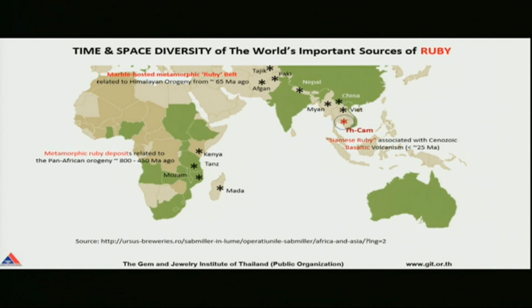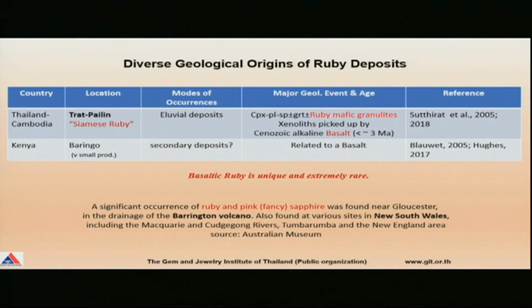Now I want to concentrate on this ruby, Siamese ruby, which is associated with Cenozoic basalt. The only place where commercial ruby of the basaltic type is found is Trat and Pailin, and we dub it Siamese ruby. It's normally mined from the alluvium deposit, and we now know that the host is actually mafic granulite, which is composed of clinopyroxene, plagioclase, spinel, garnet, and some rubies. That's picked up by basalt at less than 3 million years ago.